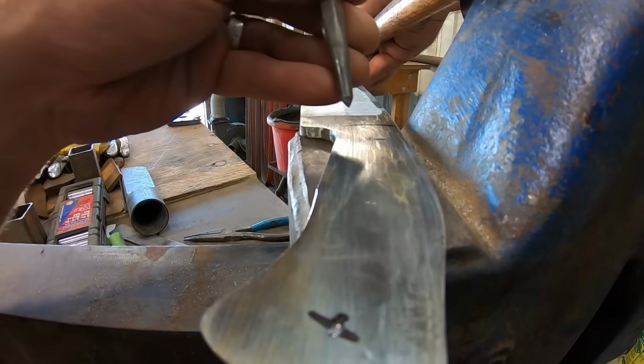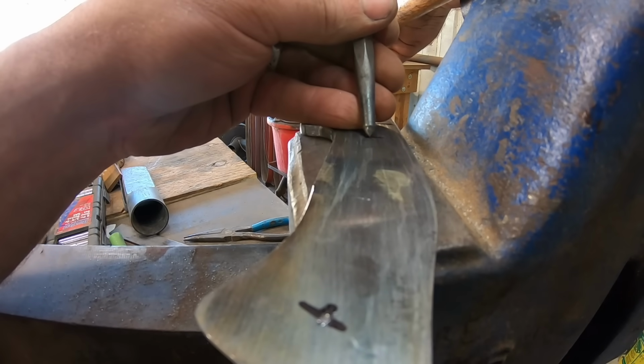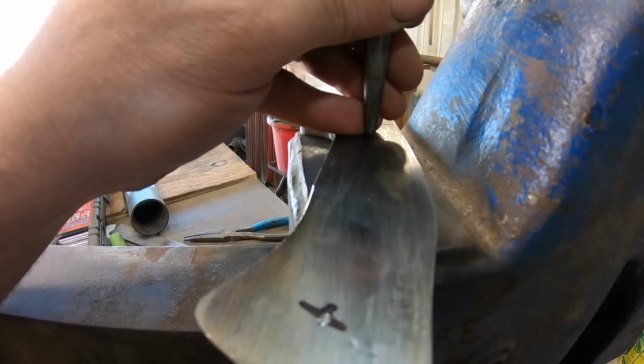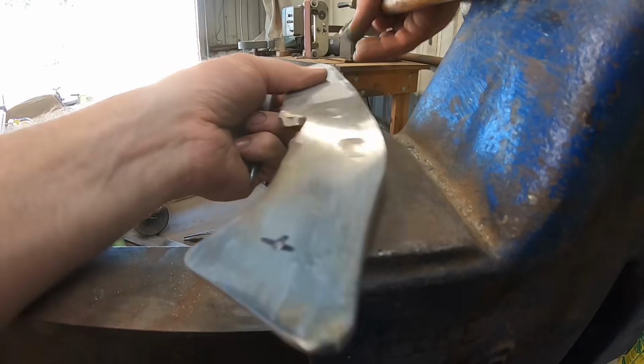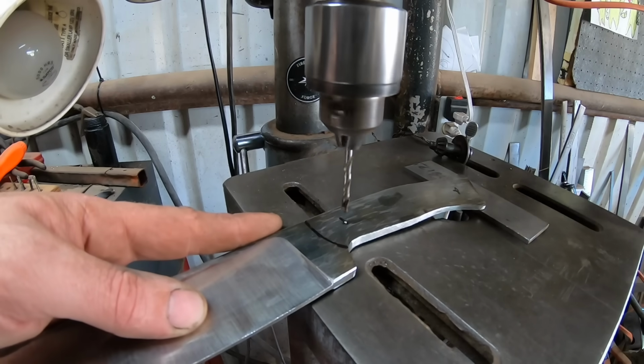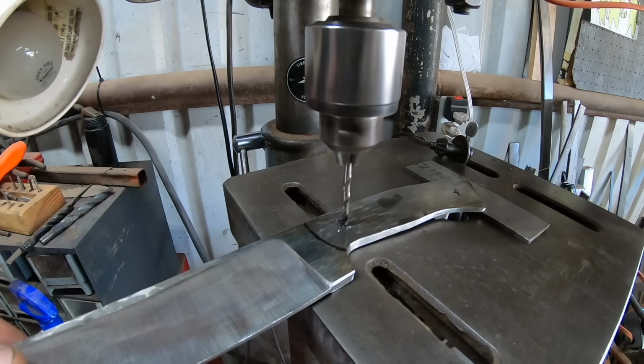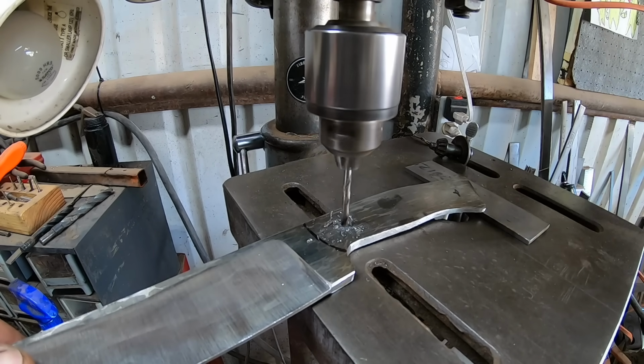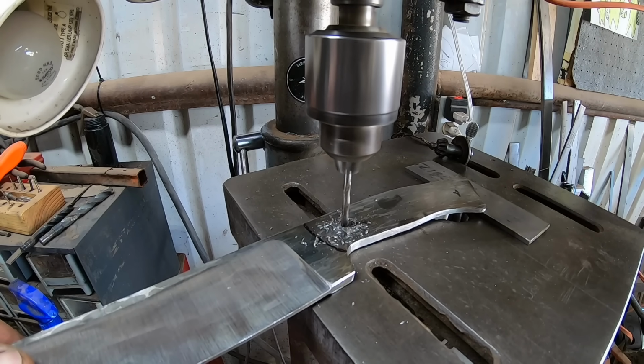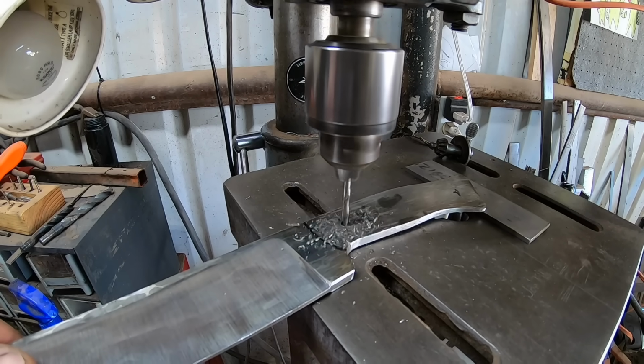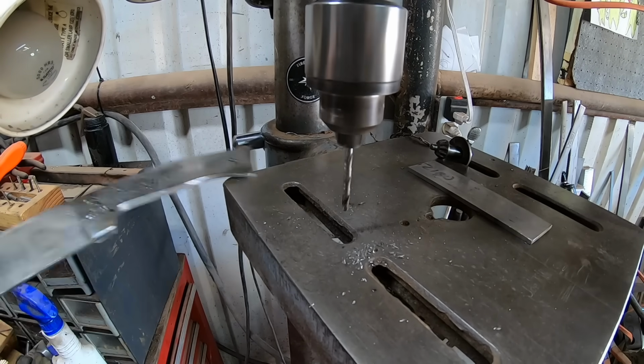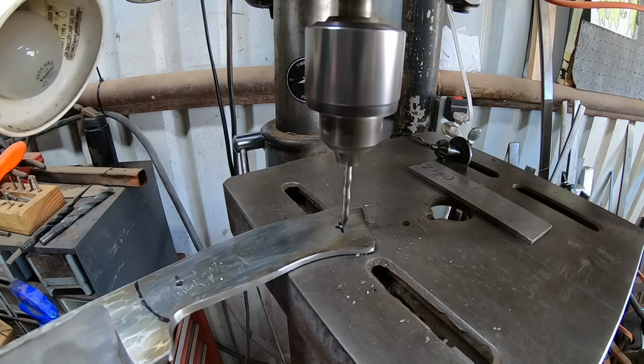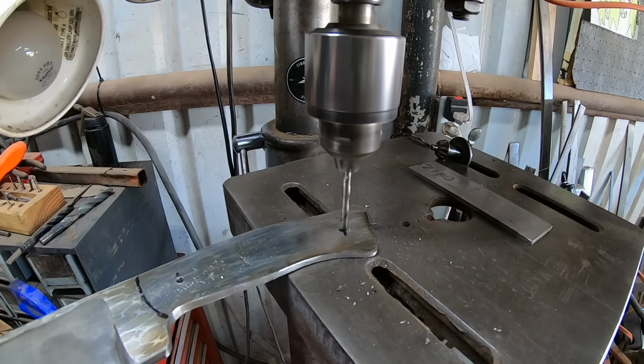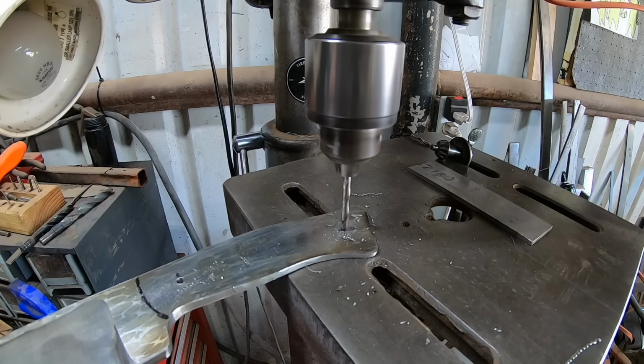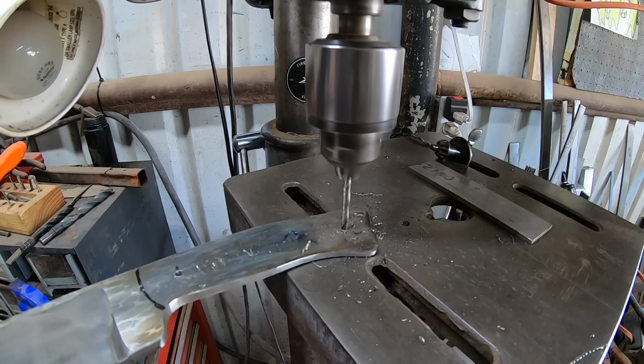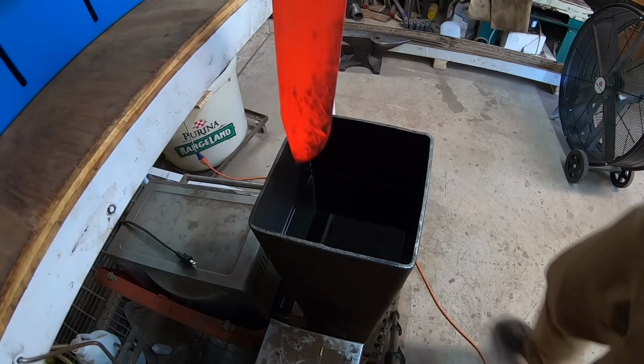So this is that steel after the process anneal, and this is actually the first time I've done it this way. And so this is a little bit of a test as well, because typically I do quite a number of thermal cycles, and this is another method that achieves the same results as far as I understand. And if I can do the same thing with less time and energy input, then that's a good thing. So we're able to drill our holes here without any trouble, which is a nice change there.